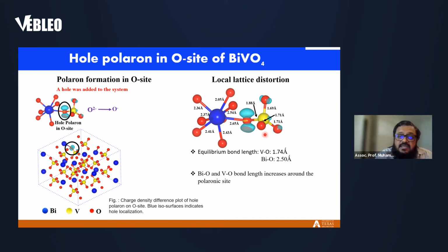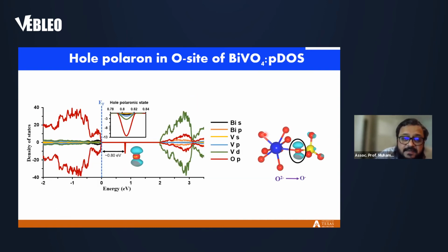And then the electronic feature shows that the hole polaron state forms at about 0.8 electron volt above the valence band maximum. Another point I would like to mention is that for both of the electron and hole polarons that we have seen, the distortion they create is very local to the site. Hence, these are small polarons that are created within bismuth vanadate.